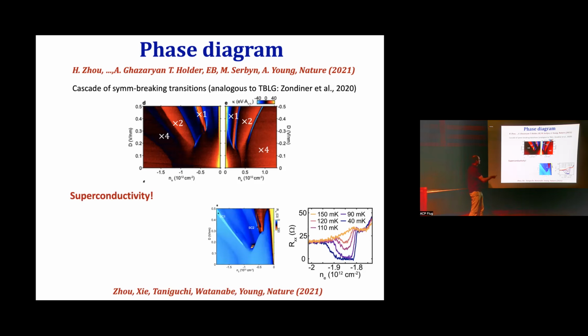And more recently, these phases are all metallic. The electrons can flow freely. And it turns out that if they looked much more carefully, they found that there's also superconductivity in this diagram. So some of these metallic phases, you cool them down enough, actually become superconducting. And this is basically the same phase diagram on the whole side.